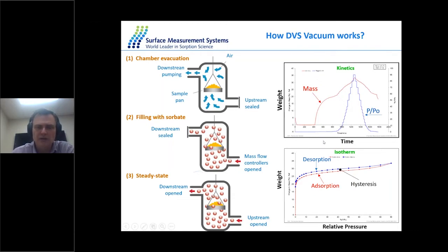With the sample at 25 degrees, I can introduce my vapor molecules. I set the partial pressure, close the downstream, and fill up the chamber with water molecules, and the sample starts adsorbing. What's happening here? The mass starts going up. When the pressure inside the chamber is below the set pressure, the valve opens. After a few seconds, we reach a steady state with a continuous flux of vapor or gas molecules on the sample while we measure the sample mass.